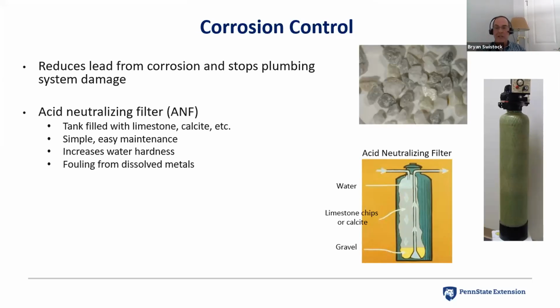You just need to replace that alkaline material maybe every 6 months, every year. It just depends on how corrosive the water is as to how frequently that tank material has to be replaced. So it's very simple, easy maintenance. One of the side effects is you get an increase in hardness, which can be a problem. Some people that are used to very soft and corrosive water all of a sudden have harder non-corrosive water, and they don't like the hardness. So you'll see sometimes that they'll install a water softener after they put this in.